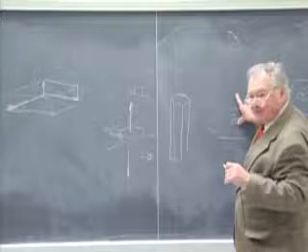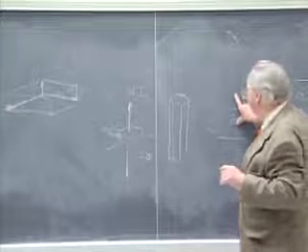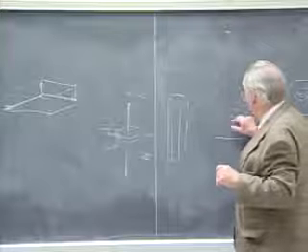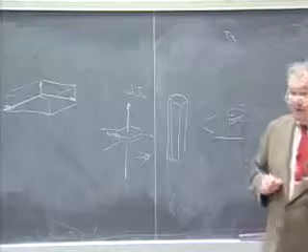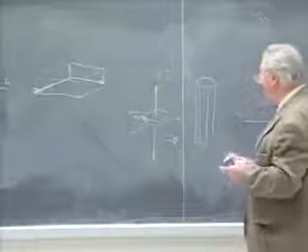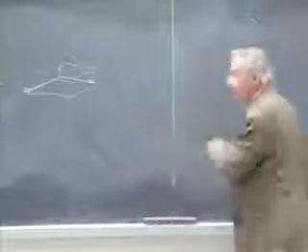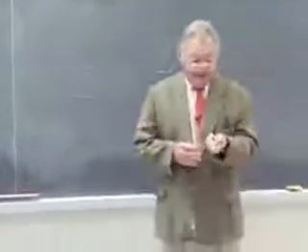So the Burgers vector would have to involve many, many layers of atoms. If the translation is very small, just 2 or 3 atoms, it doesn't cost you much work to make a screw dislocation. So I think that is the reason why crystals with very short lattice translations grow most rapidly in that direction, because it's easier to make a screw dislocation with a Burgers vector that's parallel to that translation.